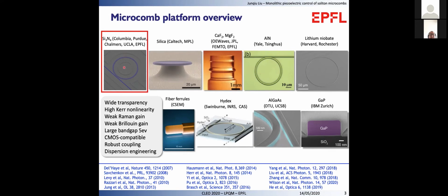Silicon nitride has several advantages. It has a wide transparency window from visible to mid-IR. It has a high Kerr nonlinearity, almost an order of magnitude higher than silicon. It has a weak Raman and Brillouin gain. It has a large band gap of 5 electron volts, which makes silicon nitride immune from two-photon absorption at telecom band. The fabrication process is CMOS compatible. Therefore, we can build robust coupling between the bus waveguide and the ring resonator. By changing the geometry of the waveguide, we can engineer the dispersion and achieve a broadband microcomb spectrum.